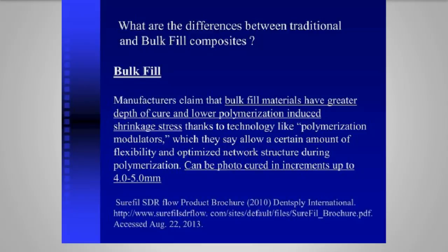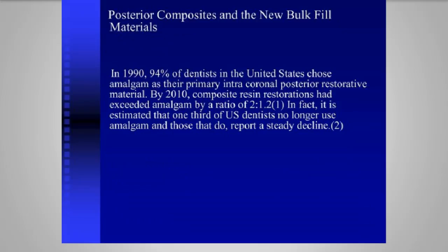So if you look at the bulk fills, they have greater depth of cure. They can be photocured in increments of 4 to 5 millimeters. Now that's a number we have to quantify and measure, because if we're over 5 millimeters, can we bulk fill if the curing lights can't get down that far?